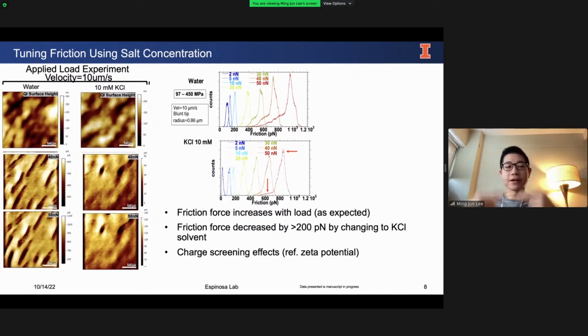And this ties back to the charge screening effects that I mentioned in the previous slide, because the surface of these hydrogels has acrylic acid groups, so carboxylic acid, that's COO minus, negative terminated. But then the AFM tip is made of silicon and it's terminated with the silanol groups, the SiO minus groups. So having negative charges on both the AFM tip and the hydrogel surface leads to repulsion between these measurement devices, and that lowers the friction force that's being measured by the AFM.